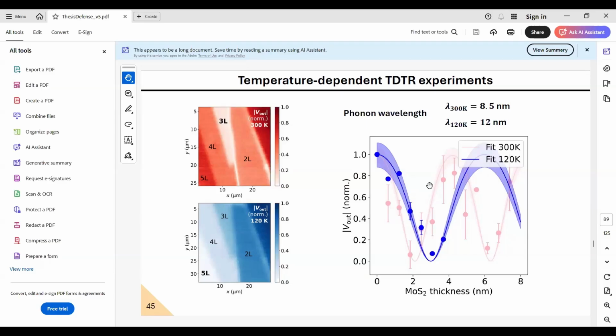Yes. Okay. Thank you for this question, because I didn't really explain how we obtain these numbers. This is, first of all, the data normalized to the substrate, so the bare substrate value. So the bare substrate is 1, and is 1 across all the time delays, except for the early times where the signal changes more significantly, more abruptly. So therefore, we average these signals, we compare them to the substrates, we normalize them to the substrate. We make the absolute value of it, because actually this would go negative and then recover positive, but we just provide the absolute value here.